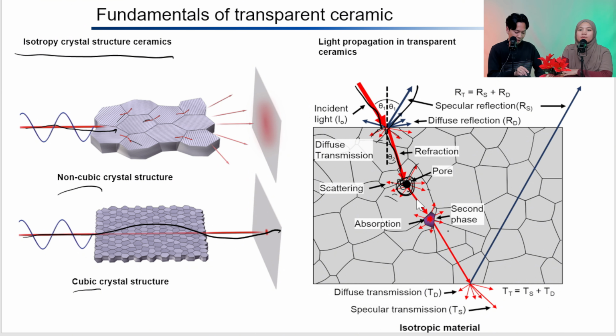Because of the different refractive index, the light will be scattered here into many different directions. Also, besides the pore, another phase or secondary phase, besides the phase of the transparent material itself, also has a refractive index, and therefore it can also scatter the light. Depending on the material, it can also absorb the light here. After that, it will be reflected again at the bottom surface of the material, so there will be two reflections here. Then in the end, it will be transmitted.